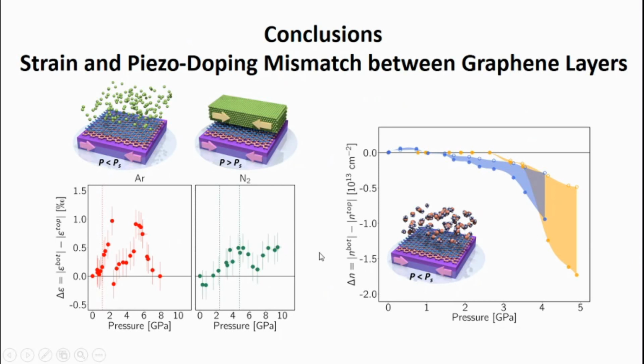We have then shown that for argon and nitrogen, a strain mismatch between the graphene layers develops with pressure. This can be used to better study the non-hydrostaticity of different pressure media. For alcohol, a polar medium, we have shown a piezo doping effect which opens a new path for piezo sensing or for strain engineering. The study of other polar media combined with modeling should allow to better understand the physico-chemical mechanism involved.